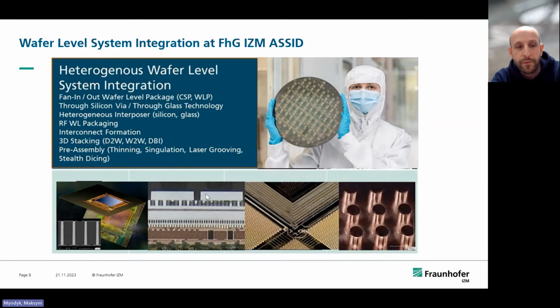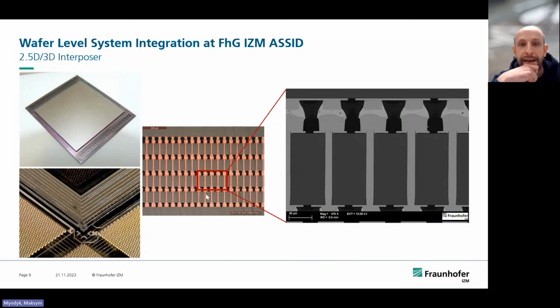But to create an interposer, something important is needed: the interconnections for heterogeneous integration. You can see these pillars there. These are vias, or TSVs, etched in the silicon wafer. But the way to get them is pretty complicated. To make them, we need a special approach, a so-called plasma etch, most widely the Bosch process. I will very briefly describe what the Bosch process is.